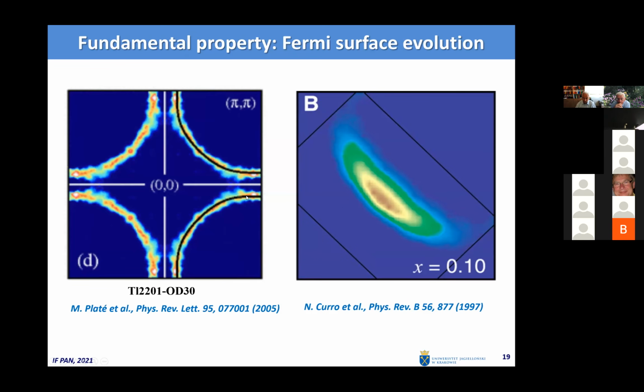As you know, these are two-dimensional metals, and on the left-hand side, as you say, case D, but of course this is taken from another experimental paper. You can see the beautiful open Fermi surface of a two-dimensional metal with two hopping integrals, one between the nearest neighbors and the second between second neighbors, because if there were no second-neighbor hopping it would be just a rhombus, whereas it gets opened. You can see the fit of this dispersion relation to the topology of the Fermi surface for the thallium compound for overdoped samples in this Fermi liquid regime.